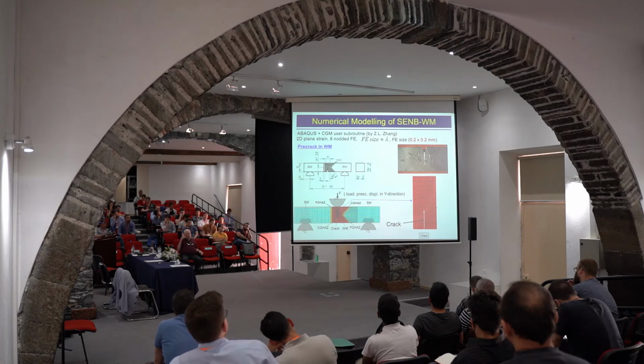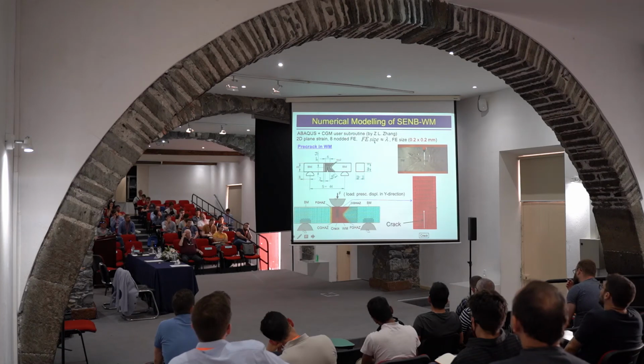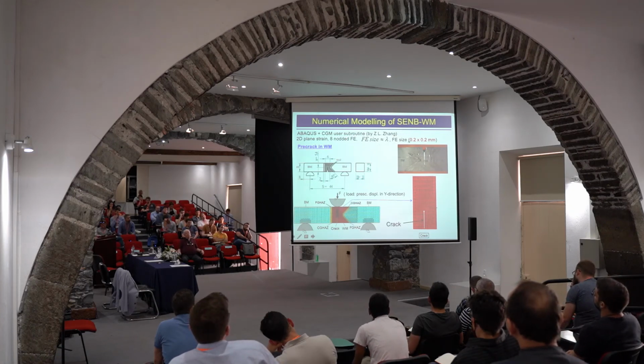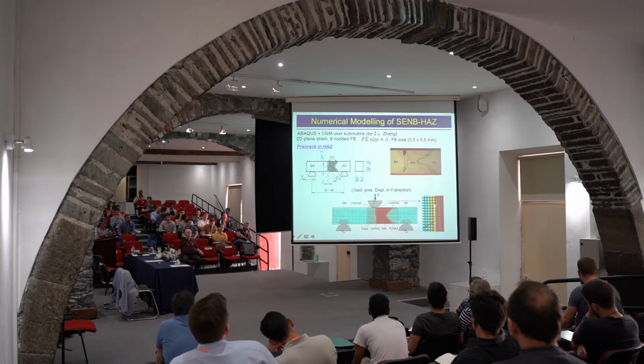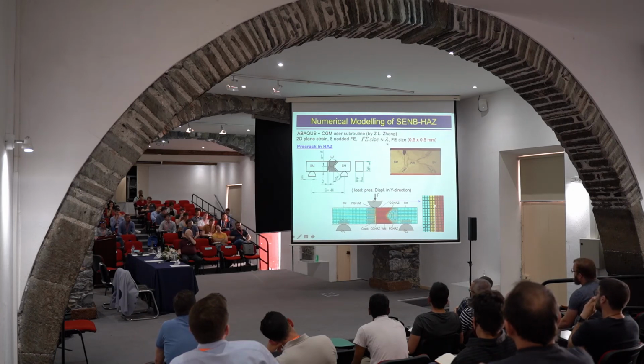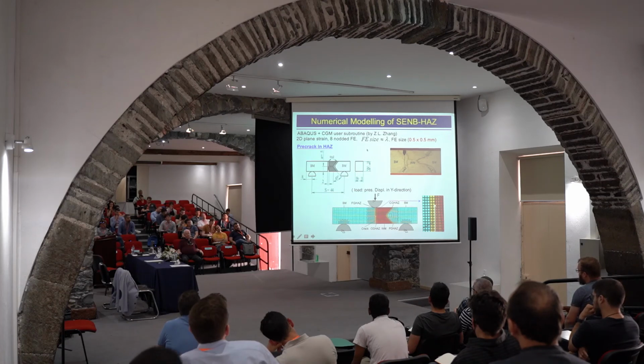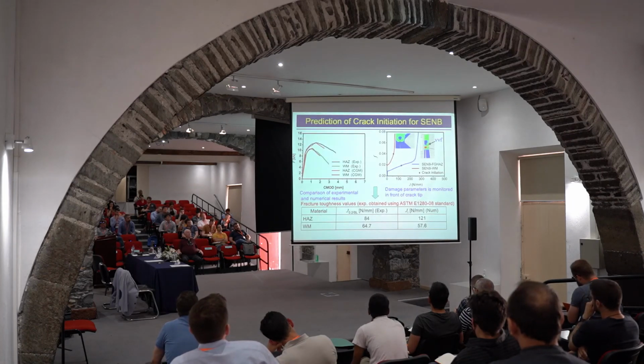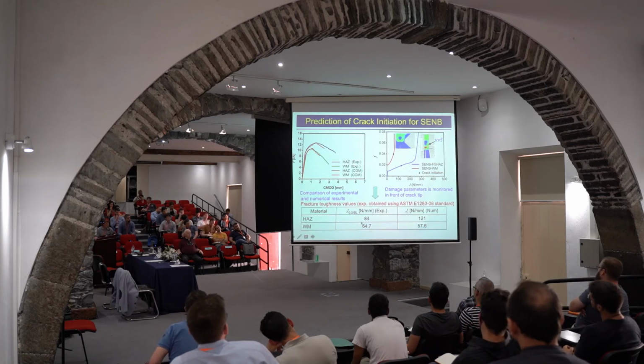So here you can see also a very important fact that finite element size was 0.2 times 0.2 in this specific case, which corresponded to the lambda value for the weld metal. In the case of heat affected zone, lambda was approximately 0.5 millimeters, so that was also the finite element size which we expected to work appropriately. And you will see here some results leading to the determination of the crack initiation point and leading to the J initiation values as shown here.